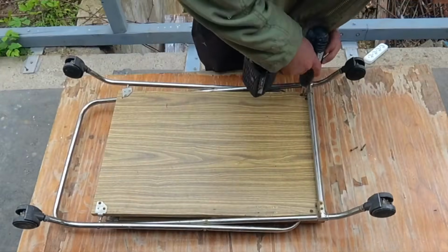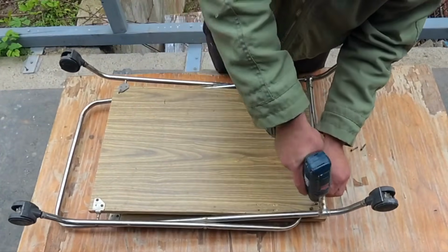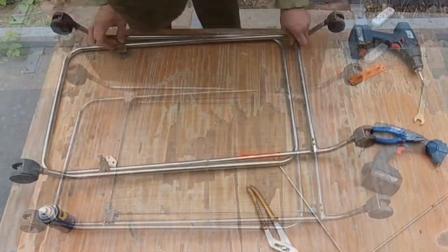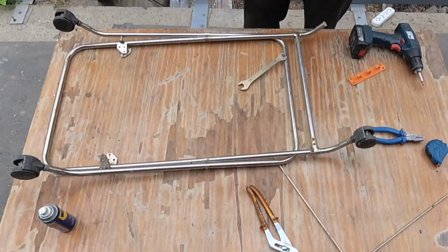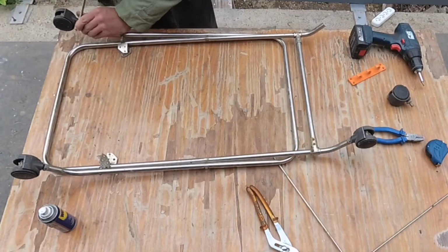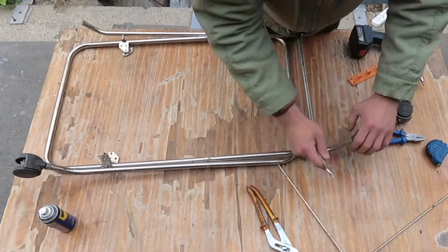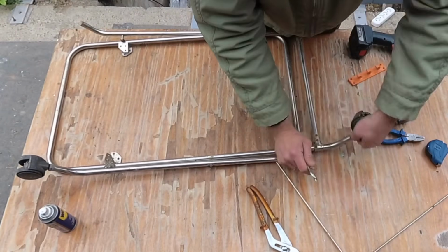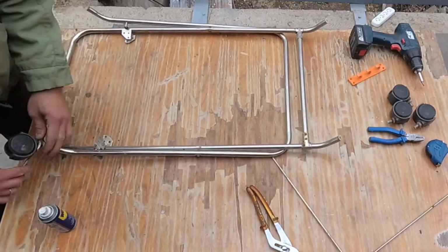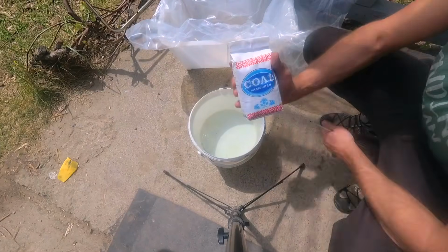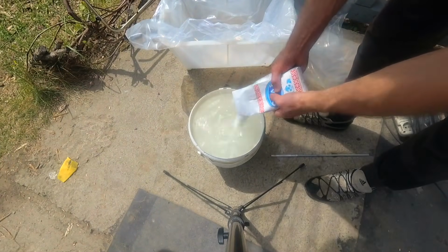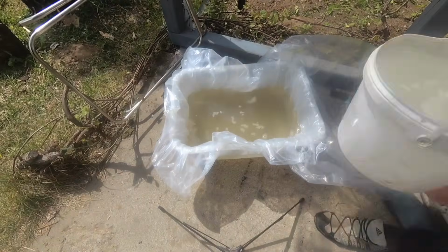The chrome on this table was pretty badly damaged, a lot of peeling and rust, so it needed to be removed. I immediately tried abrasives, but after a couple of minutes, I realized it was useless. I found out that galvanic chrome can be removed. I did some more research online. I decided to try salt. I made a salt solution of about 1 part salt and 5 parts warm water.